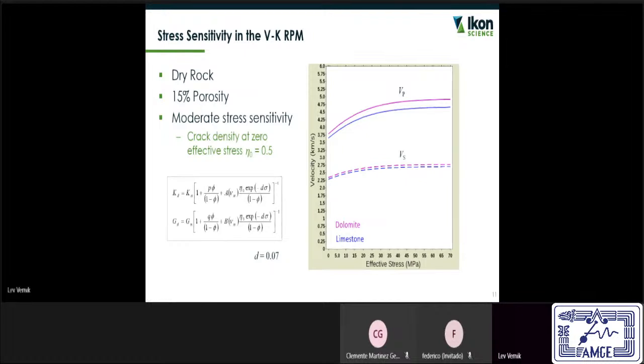Well, imagine that you have microcracks that would be very low aspect ratio, and they would be stress sensitive. Under certain stresses, they will close. They will tend to gradually close. And this gradual closure of microcracks leads to nonlinearity at relatively low to intermediate effective stresses. And then finally, you reach the plateau where the velocities would not change dramatically anymore. So again, this same model, without any specific calibration, can be used for stress sensitivity analysis as well.